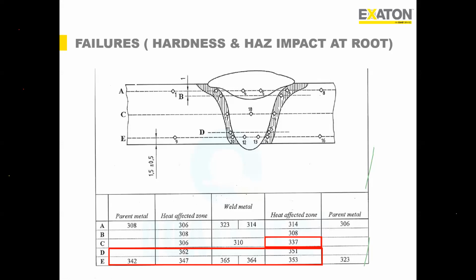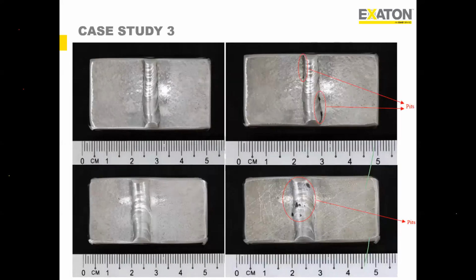So this is also a lesson learned for us, that using a higher alloyed filler metal is not always necessary. Yes, it gives protection on the corrosion property, but at the same time, you might also have to sacrifice your hardness. So that's where it is basically like a juggling for any duplex family. What is your desired requirement on the project? Depending on the requirement of the project, we should make a balance of the parameters and selection of the filler metal.